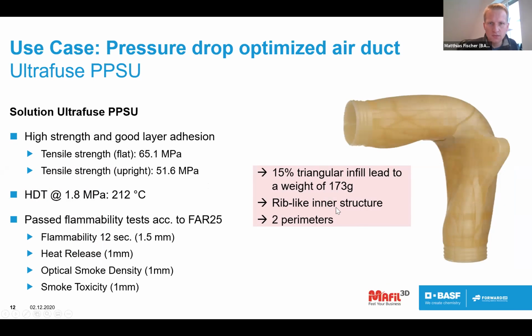The motivation to use a PPSU in this case was that this filament has very good mechanical properties in the flat orientation, about 65 megapascal, but even upright, printed on a printer with a heated chamber at around 180 degrees C, we still have about 50 megapascal in tensile strength. If you see the picture here on the right side, you can see this connection area. You can see that we used a reduced infill. That's also why you have this triangular structure in this component. But the combination of the reduced infill and the material made the part really extremely stiff. And it was at the end of the day 173 grams and printed with two contours.